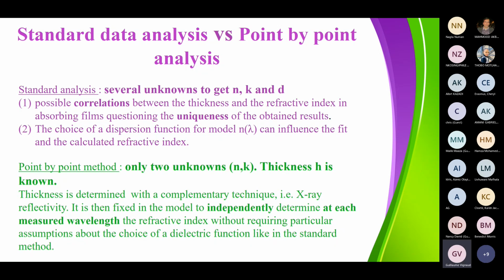Then the advantage of this approach, of course, is that there is no correlation between h and the refractive index, and also you don't need to define the dispersion function, because this function depends on the sample that you are studying. For example, if it is a polymer film, an insulator, a semiconductor, or a conductor, it is not the same law to describe the evolution of the refractive index. It's sometimes difficult to know what is the best law to define the sample. In particular with VO2, because sometimes you have a mixed coexistence of two phases, of two structures, the monoclinic and rutile phases, and it's difficult to say what is the best dispersion function.